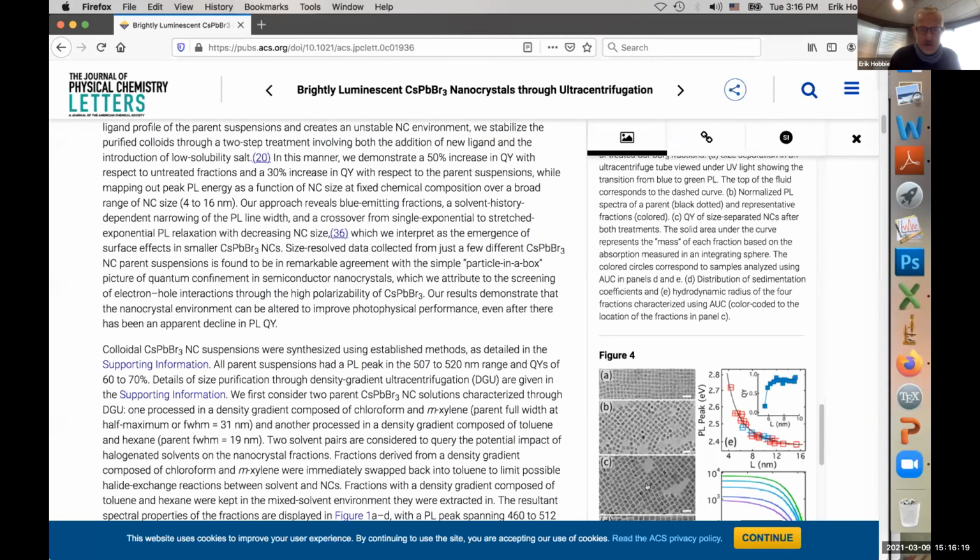Is the Bohr radius for chlorine smaller than bromine? It is. Okay. So that would suggest that in the case of chlorine, this curve should shift this way. So maybe it is confinement, but you're on this really, really weak screened confinement. It's got to be screened, yeah, L^-2, right? So a safe bet would be that chlorine is the same, but just shifted to lower length scales, but you still have a size dependence here, right?